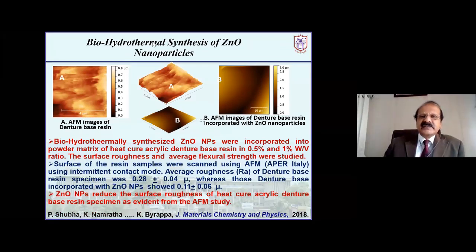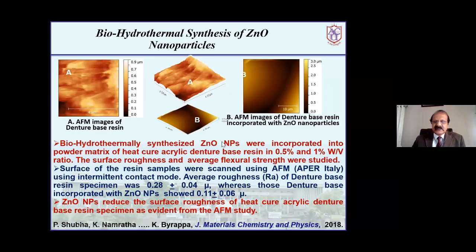Now this one shows biohydrothermally synthesized zinc oxide nanoparticles. We have tested the surface roughness of zinc oxide synthesized using these, on the denture base. We have distributed these hydrothermally synthesized zinc oxide nanoparticles on the heat cured acrylic denture base resin in 0.5% and 1% weight per volume ratio. The surface roughness and average flexural strength were studied. And the interesting thing is, zinc oxide nanoparticles reduce the surface roughness of heat cure acrylic denture base resin specimens, as evident from the